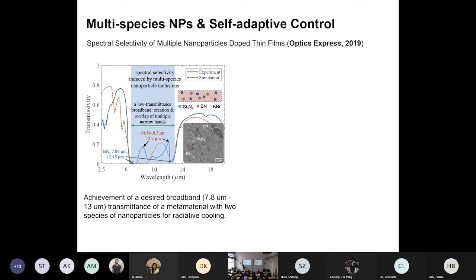You can see, if we simply use one species, silicon nitride, you're going to see two narrowband emission peaks at 8.5 microns and at 12.2 microns. If we simply use boron nitride, you're going to see two other peaks, 7.09 and 12.445 microns. So you can imagine if we combine these two materials, we might be able to see four separate individual emission peaks, or we might be able to open up a broadband. We did this experimentally, and we found that we're able to open up a broadband thermal emission window. This is the concept.